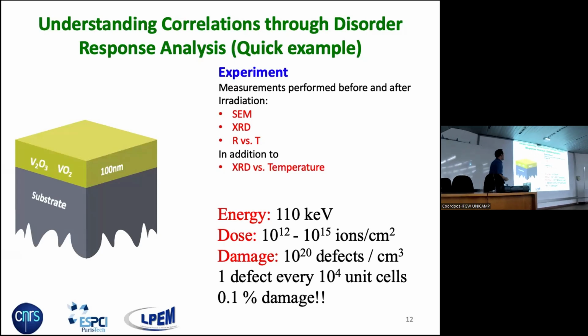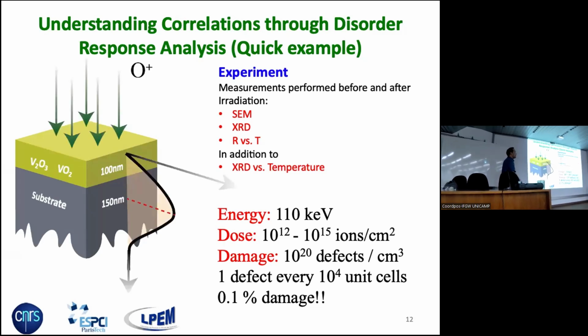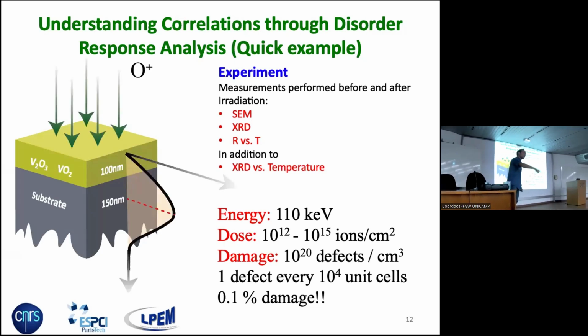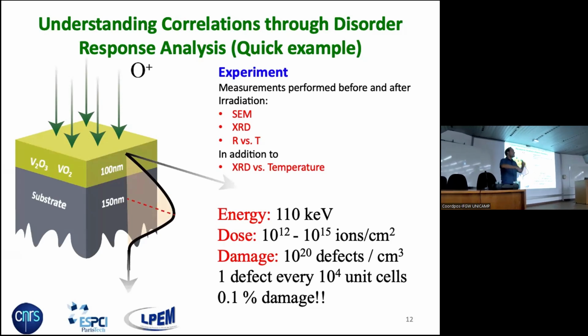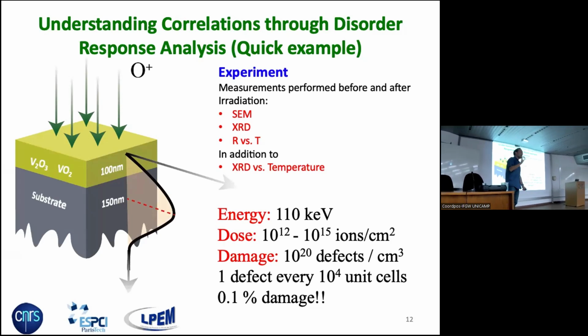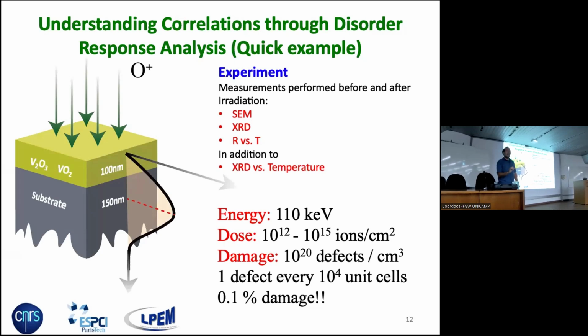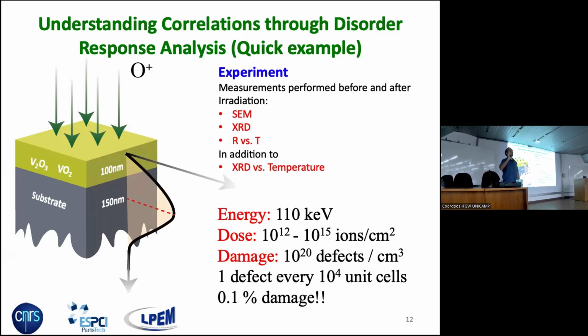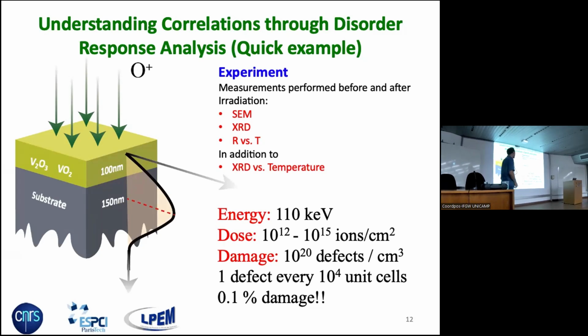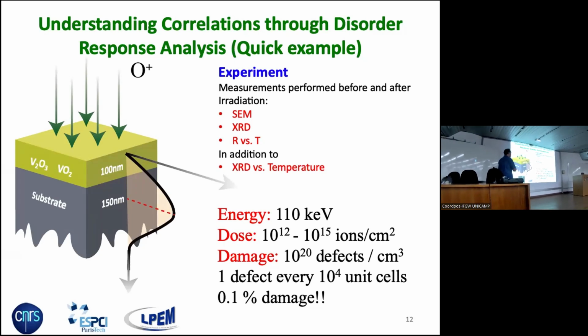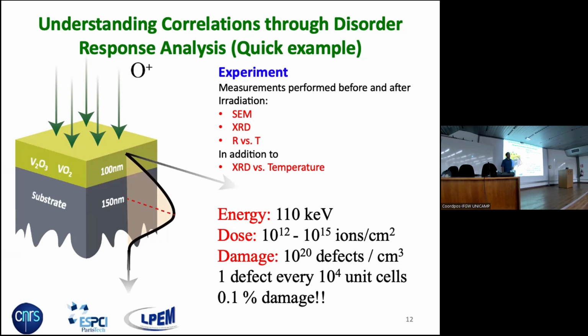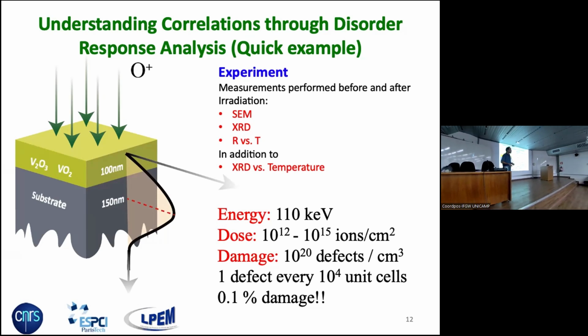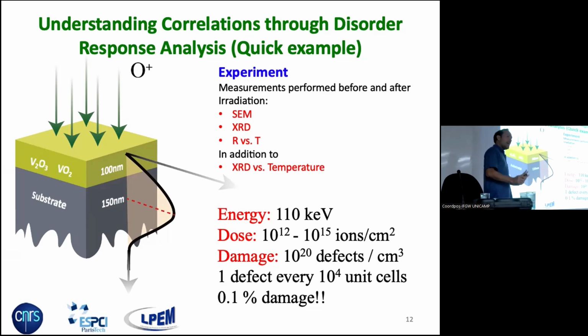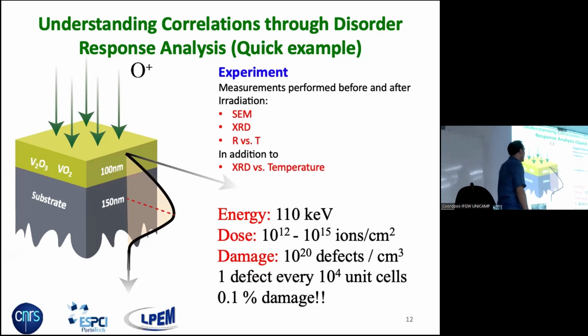So how do you disorder this? You induce some radiation damage. You send ions with a particular energy, and then you knock out some atoms, you create some vacancies, you create some dislocations, and you can tune how much disorder you create in the material. This is the profile of where the ions end up. As you can see, most of the oxygen ions end up in the substrate, so they just go through the vanadium oxide, and my point here is that the damage you are doing is very tiny, as I said at the beginning.